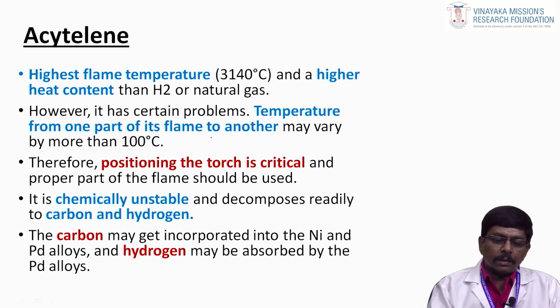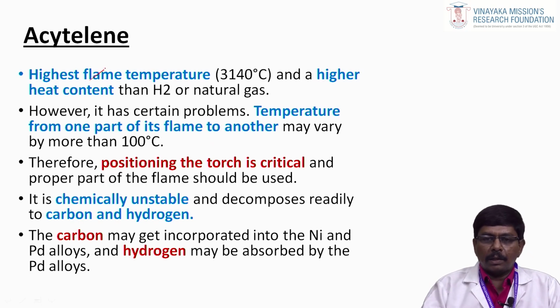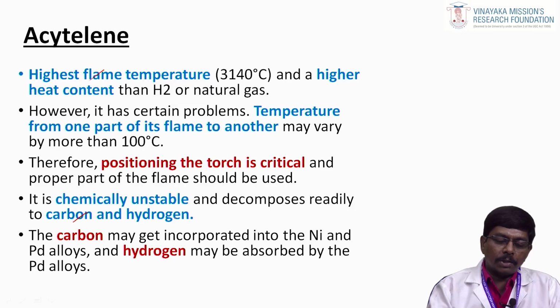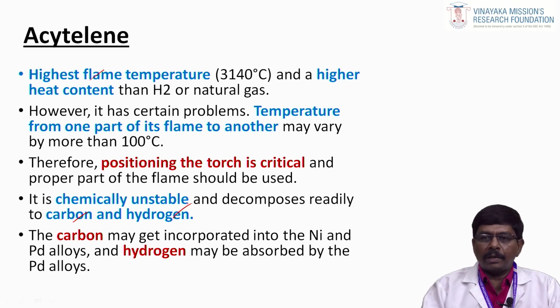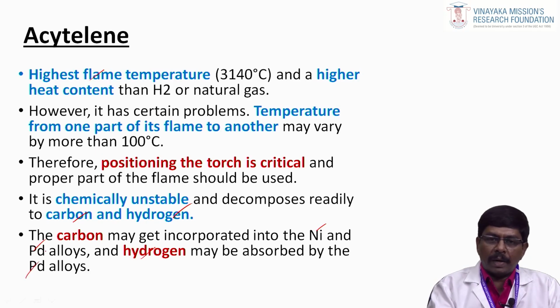Coming to acetylene gas, it has the highest flame temperature, and higher heat content than that of H2 and natural gas. But the problem is that the flame temperature varies by more than 100 degrees centigrade in different parts of the flame. Positioning the torch is also very critical. The proper part of the flame should be used. Chemically it is also unstable, decomposing to carbon and hydrogen. Carbon may be incorporated into nickel and palladium alloys. Hydrogen may be absorbed by the palladium alloys.